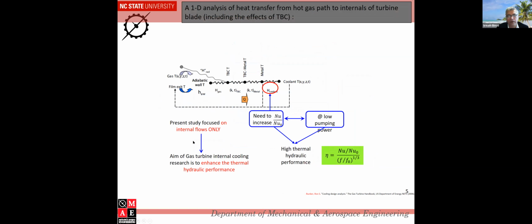So as a heat transfer person, I look at it as a simple 1D analysis here. I got a gas hitting my outer wall, and there's a heat transfer coefficient associated with that. And I have that as a convective resistance. Of course, there's the radiative resistance also, which is also added here. And the TBC coating itself, the interface resistance, which I have not added. Then you have the thermal conductivity of the TBC and the thickness of the TBC that dictates the heat transfer into the blade. And then you got the interface between the TBC and metal where the bond coating is.